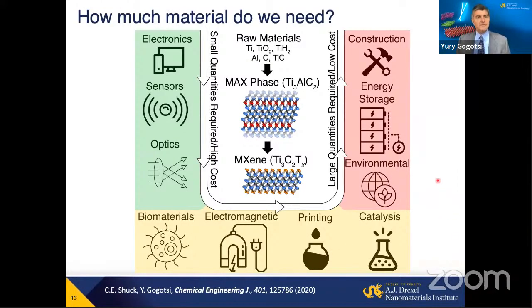It has its limitations. We may not get absolutely perfect and ideal particles. We get surface termination, but there are also big advantages. If you look at the great majority of two-dimensional materials and nanomaterials in general, and there are a couple of hundred 2D materials already, more than 200 reported, most of them are produced in microgram, milligram, or gram quantities. Two-dimensional boron, two-dimensional gallium arsenide, gallium nitride have been produced basically as monolayers, need protection not to degrade, and their application may be limited to sensors, electronics, something with a very small amount of material required. If we want to move towards biomedical applications, conducting inks, electromagnetic shielding, catalysis, and of course, even more so large-scale energy storage or generation or construction materials, we need much more.